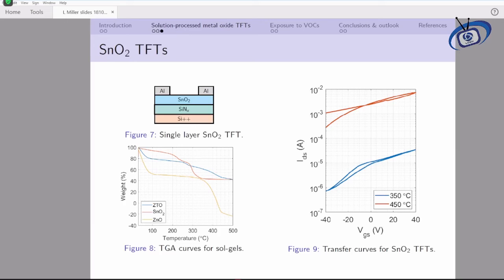Thermogravimetric analysis, or TGA, was performed to illustrate the different stages of solution processing and provide the optimum annealing temperature of the films. The TGA curves for each sol gel are plotted in Figure 8. You can see that the graph is divided into 3 sections.